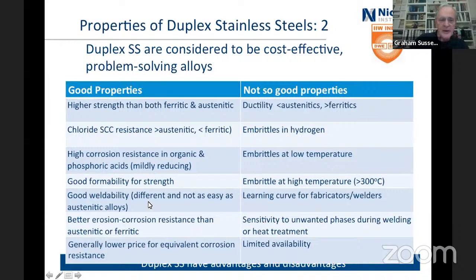Good weldability, it's different from the austenitics, but not quite as easy, but you can still weld it reasonably well. It's a learning curve for both fabricators and welders. Erosion corrosion resistance better than the austenitic and ferritic. I think you saw the note I put up earlier saying it's about 3 times better than the 316. It is sensitive to unwanted phases that happen if you're welding or you're doing a lot of heat treatment.